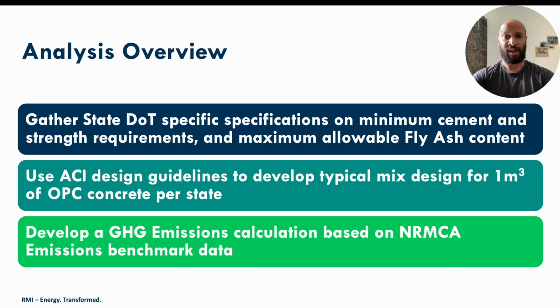We conducted an analysis to find the potential greenhouse gas emissions of these states. We did this by gathering state DOT specifications on minimum cement and strength requirements and maximum allowable fly ash content. ACI design guidelines were then used to develop typical mix designs for 1 cubic meter of ordinary Portland cement concrete per state. Following on from this, a greenhouse gas emissions calculation based on the NRMCA emissions benchmark data was developed. Next slide.